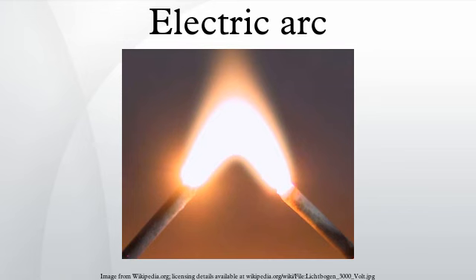Electric arc over the surface of plastics causes their degradation. A conductive carbon-rich track tends to form in the arc path, negatively influencing their insulation properties. The arc susceptibility is tested according to ASTM D495, using bipoint electrodes and continuous and intermittent arcs. It is measured in seconds to form a track that is conductive under high voltage, low current conditions. Some materials are less susceptible to degradation than others. For example, polytetrafluoroethylene has arc resistance of about 200 seconds.